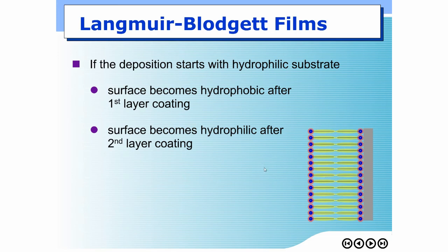So if you repeat the pulling up and the pushing down like this, you can form the layers that you want. Of course, it depends on the application and the type of surfactant molecules. If you have surfactant molecules containing metals and maybe a long chain of hydrocarbon, once you form this layer and you heat it up, that hydrocarbon part would be burned, and eventually you will end up with a metal oxide layer.